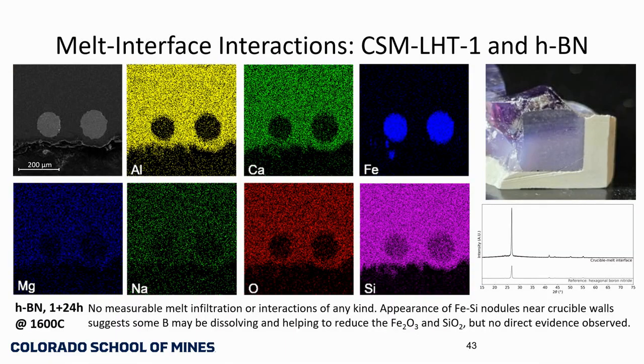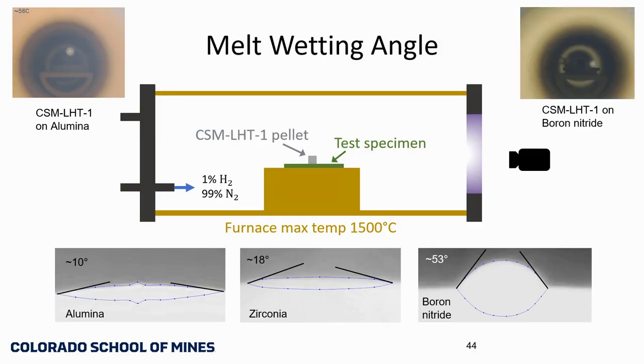There's a little bit more closely on molten CSM LHT1 with hexagonal boron nitride. There is some reaction. We find this interesting thing that iron spheres develop at the wall. We are doing this in a slightly reducing atmosphere, a little bit of hydrogen in there to extract the oxygen that's being formed. But this has led us to conclude boron nitride is reactive, but it's a relatively good balance between non-reactivity and compatibility with a lot of the materials.